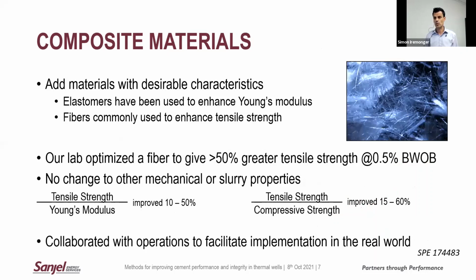We've seen a lot of great talks already on this, essentially using a composite materials approach, where you add a second material to your cement to try and impart some of that material's characteristics onto your bulk cement. Elastomers have been widely used to enhance the Young's modulus. But one of the difficulties is that the Young's modulus of your elastomer isn't that vastly different to that of your cement. So you typically have to add very large loadings to get substantial changes to your cement's Young's modulus, and that can sometimes impact the potential value to the client.